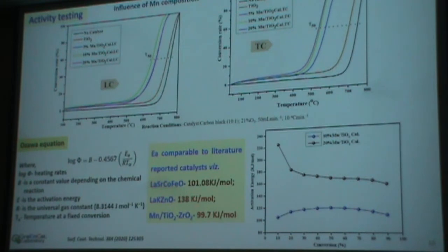As you can see, in loose contact mode, for soot oxidation the 10% Mn loading shows higher activity compared to the 20%, whereas in contrast, in TC mode both 20 and 10% loaded Mn show almost similar activity. Then why is there such a difference, although there is higher Mn loading on the catalyst surface? We also calculated the activation energy for both systems, 10 and 20%, and 10% shows a much lower activation energy, which means it is highly active for soot oxidation compared to 20% Mn.